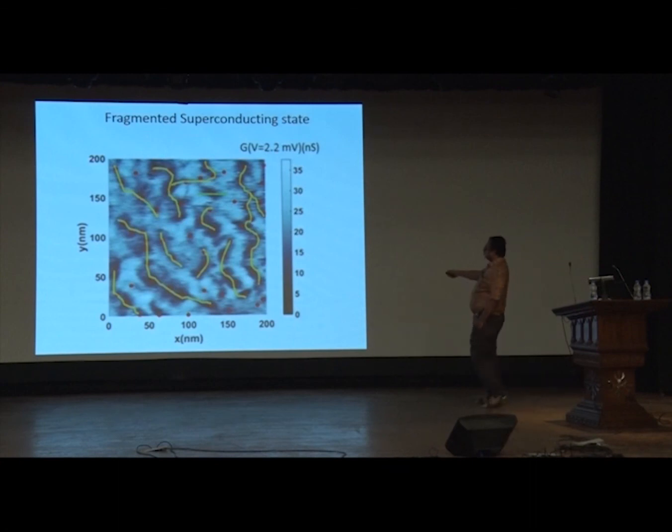Now if I look more closely, you can see that these vortices enter like these lines, like these chains, and they form this kind of a lamellar structure. So I start essentially segregating my superconductor into regions where there are vortices, and since there are vortices there, the superconducting order parameter is suppressed, and they segregate my system into these whitish puddles where I have a robust superconducting order.